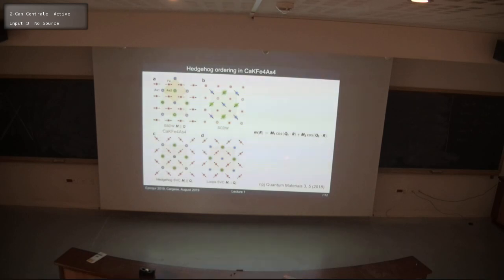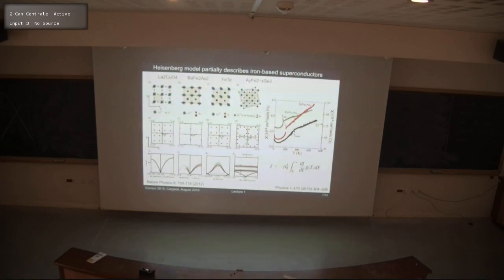And since then, it's been found that magnetic ordering can vary quite significantly between different families, and here is just various types of ordering from collinear antiferromagnet to hedgehog-like ordering, where you have in and out spins varying on this iron lattice, and due to the variation of magnetization between different sites. So magnetism is not universal. When the systems seem to be quite itinerant, it seems to be collinear antiferromagnetic, but it deviates in many other classes of materials.